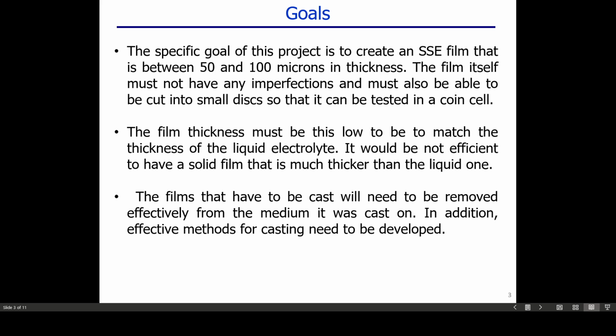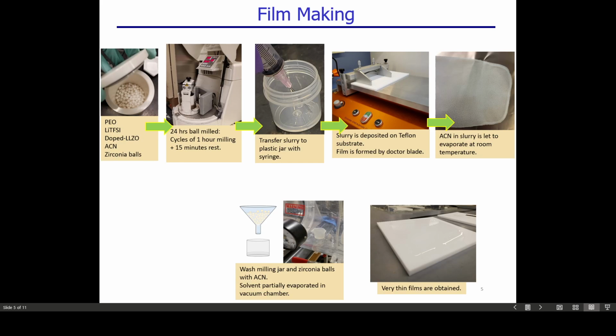The films must also be cast on a medium that it can be easily removed from, so therefore effective casting methods need to be developed. The initial method for making this polymer electrolyte film was to use the LiTFSI salt and PEO, which is polyethylene oxide, those two solids, dissolve them in a solvent and in a temperature bath, and get a slurry.